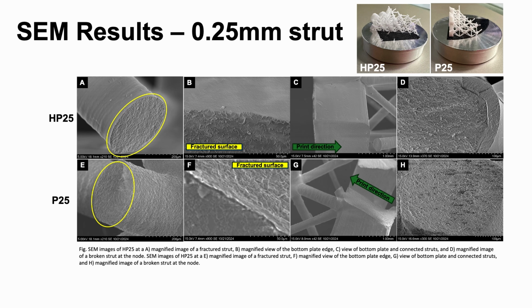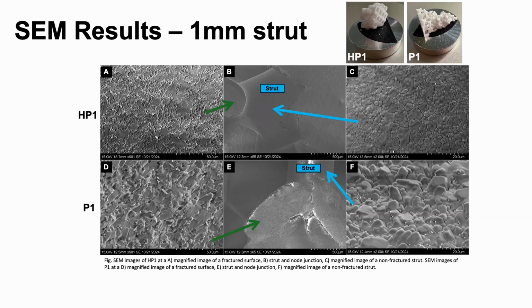In images C and G, we can observe the way that the parts were printed by looking at the layer-by-layer design. In G, the layers are very distinct, possibly from poor interlayer adhesion in P alumina. When we look at the broken strut closer to the node, we see that there's a high surface roughness in both D and H images for both alumina purities.